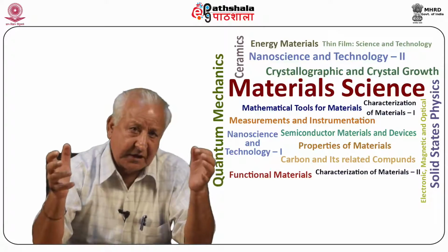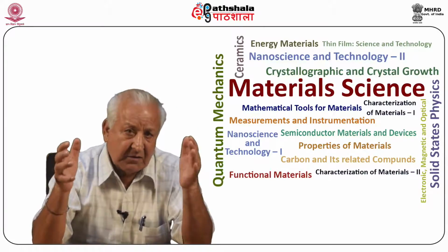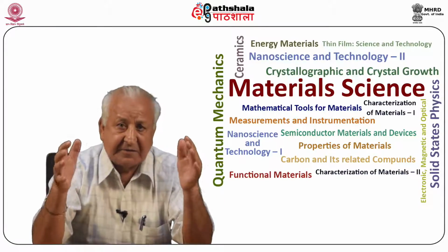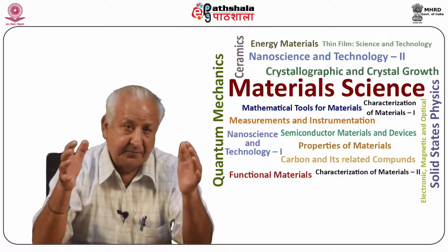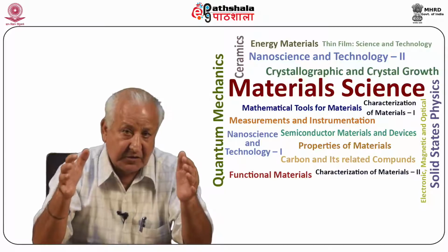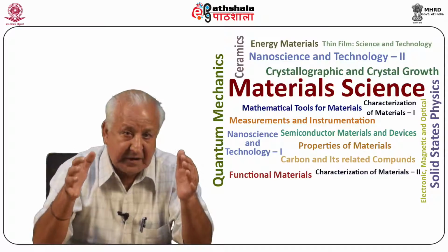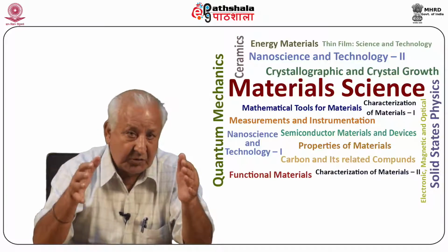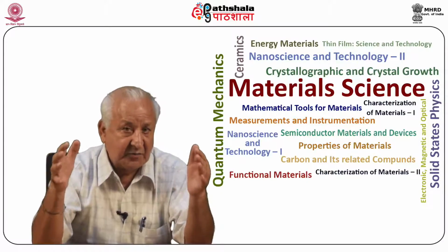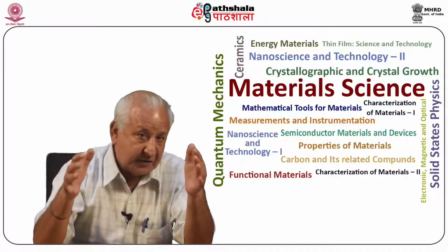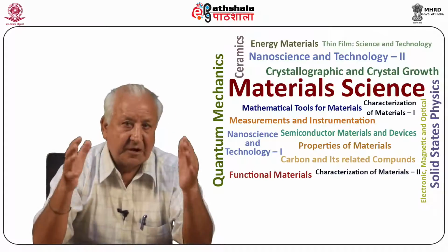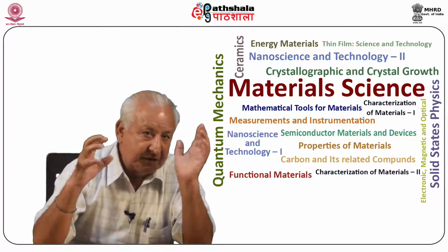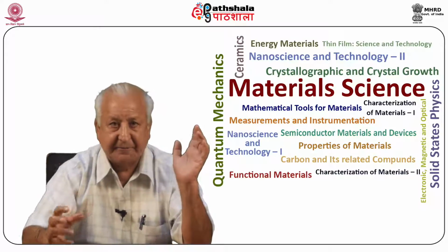The second type of dislocation is screw dislocation. Now let us describe screw dislocation. Burgers introduced the idea of screw dislocation in 1939. It is also called Burgers dislocation. In this case, the displacement b, that is the Burgers vector, is parallel to the dislocation, as is shown in figure 16.5. In this type of dislocation, the crystal is not composed of a set of parallel planes but consists of a screw ramp which rises along the dislocation line.